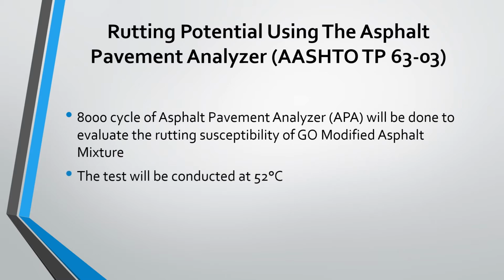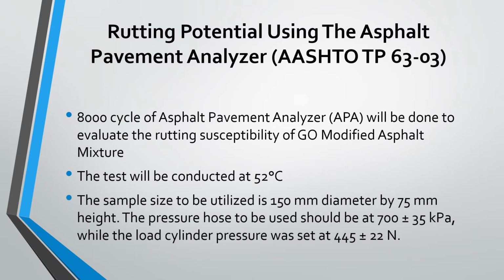The sample size to be utilized is 150 mm diameter by 75 mm height. The pressure hose should be at 700 plus or minus 35 kPa, while the load cylinder pressure was set at 445 plus or minus 22 newtons.